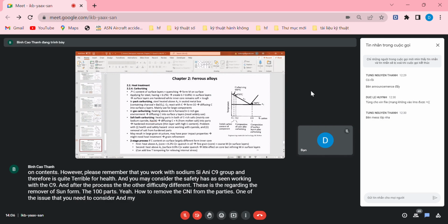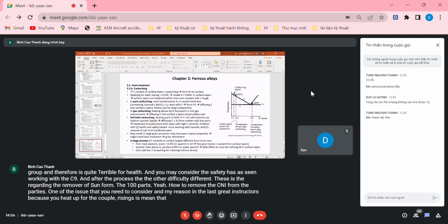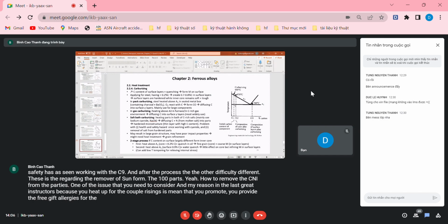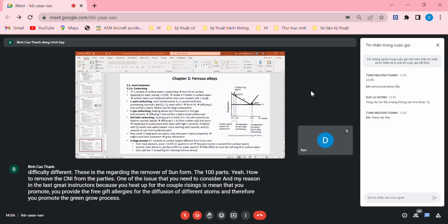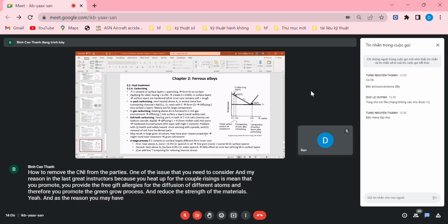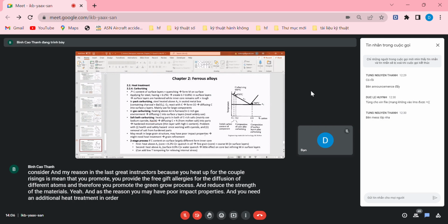It may also result in large grain structures because you heat up for carburizing. It means that you provide free energy for the diffusion of atoms, and therefore you promote the grain growth process and reduce the strength of the materials. As a result, you may have poor impact properties, and you need additional heat treatment in order to refine the grains.